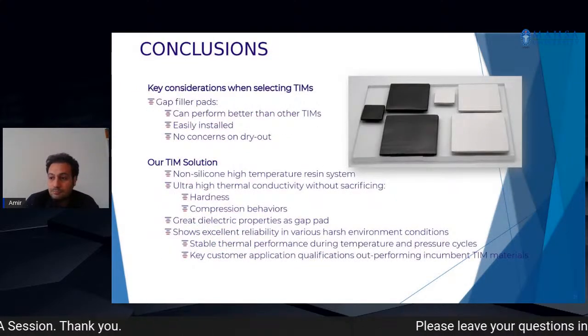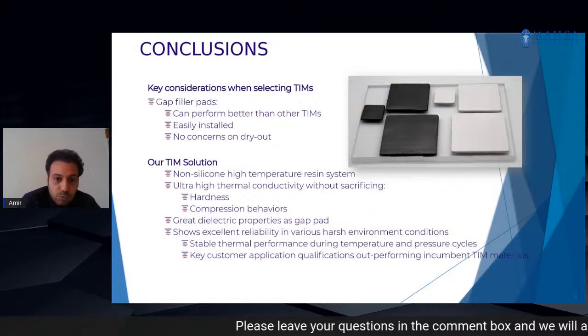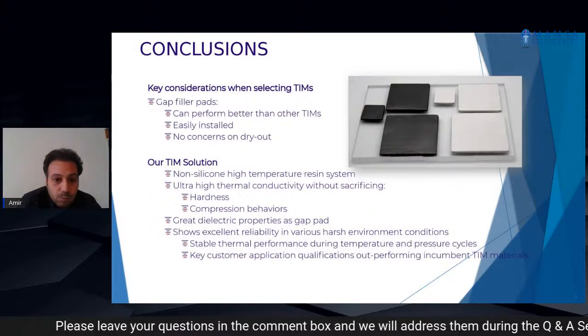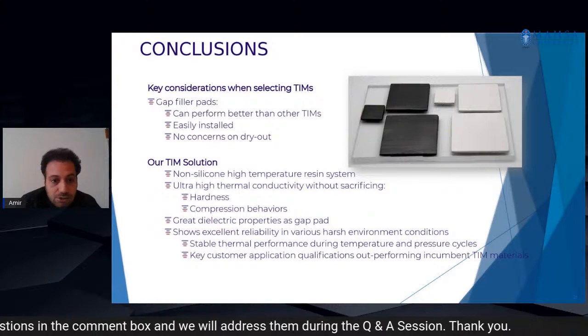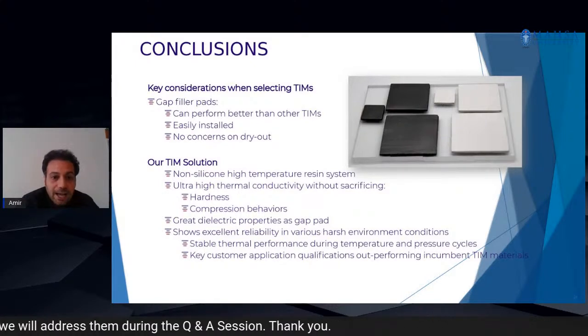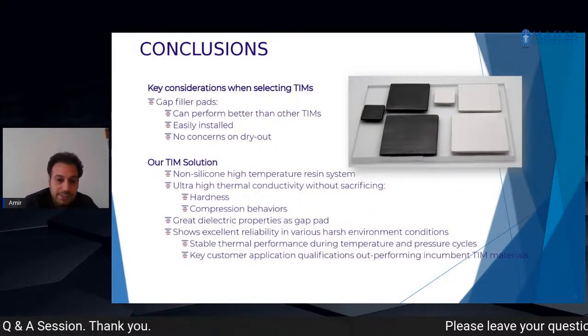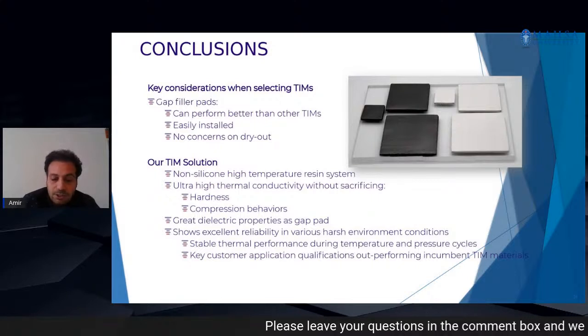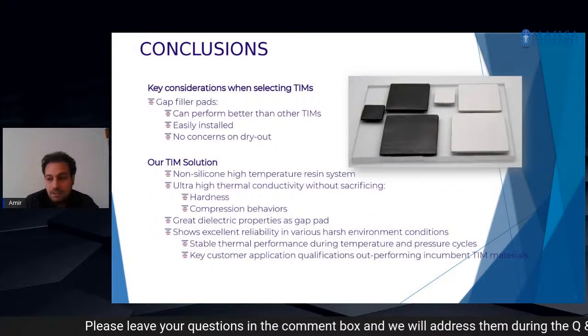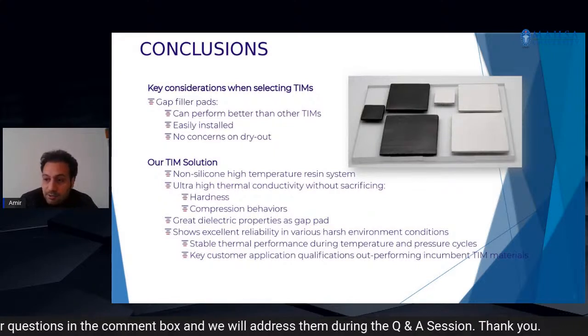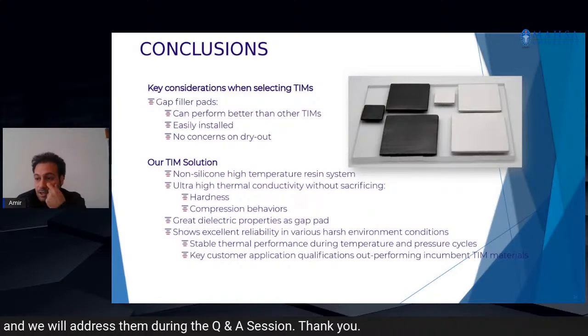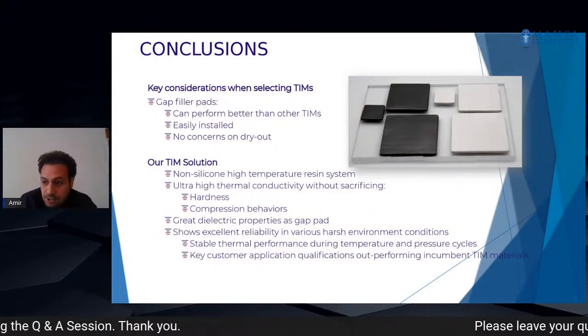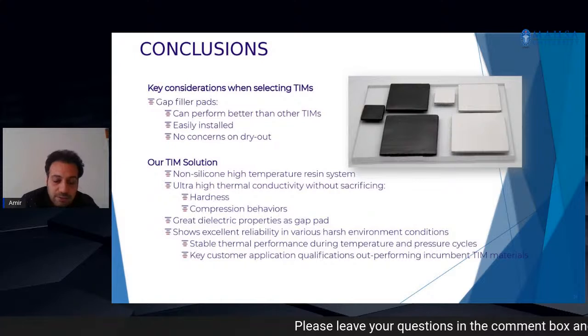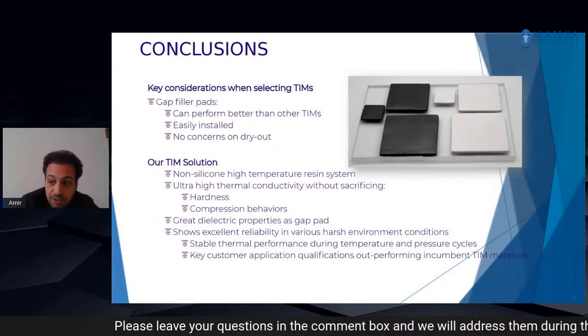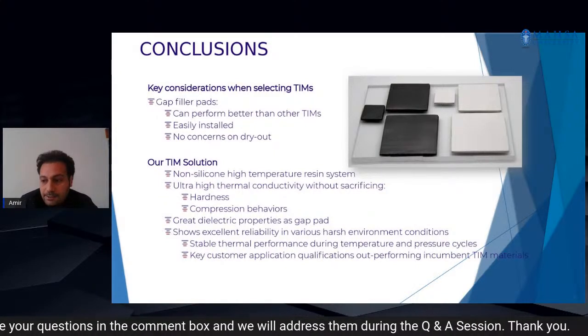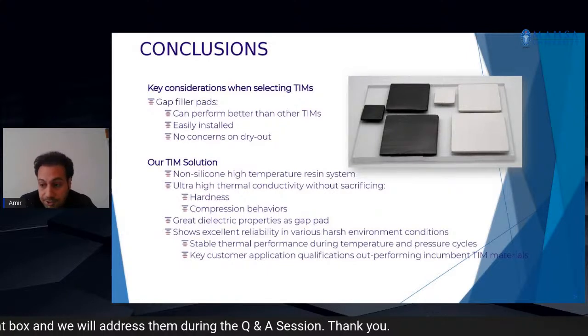In conclusion, the key consideration when selecting a thermal interface material is that it's important for us to have a good gap filler, performing better than other commercial ones, easy to install, with no residual on the system. The carbon-based filler is what we are focusing on, non-silicon, and also low thermal impedance. We have two different kinds of samples: one is highly thermally conductive, 2-3 times higher than the commercial ones, and the white one is electrically insulative.